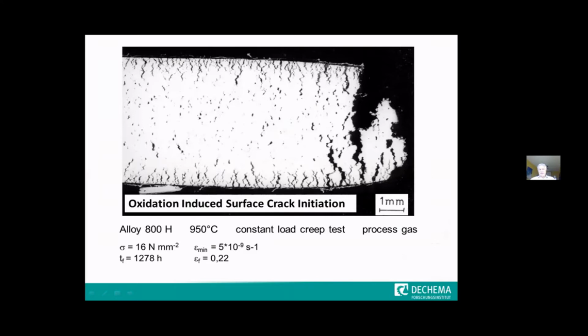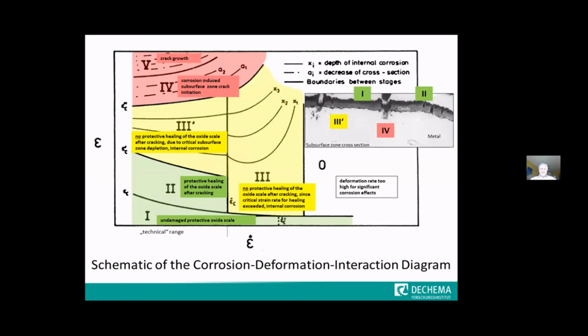So you can see that all these oxidized grain boundaries close to the surface were evidently very brittle under such conditions. That means even in the creep test at 950 degrees C, where the metallic material would be quite ductile, this would be enough that by grain boundary embrittlement, these grain boundaries can start cracking at high temperatures. Now, there are a couple of different stages that can happen and finally end up in failure of the material. This was at the beginning of the 80s, and that's why you see that it's quite a historic slide here.